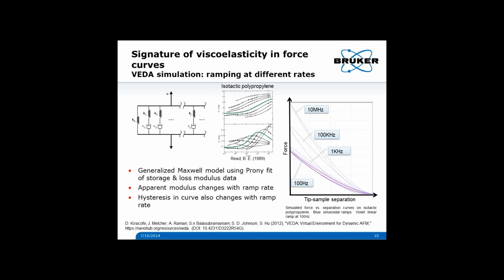But to get a feeling for qualitatively how force curves might behave at different ramp rates with a viscoelastic material, we looked at using the VEDA simulator to actually calculate out what some force curves would look like, given a generalized Maxwell model of isotactic polypropylene. So we took data from this Reed paper here, where we have storage and loss modulus as a function of frequency, and this green line is actually the room temperature line. We did a Prony fit of this, which fills in the components of the Maxwell model, and then we're able to use the VEDA simulator to calculate out what the force curves should look like.